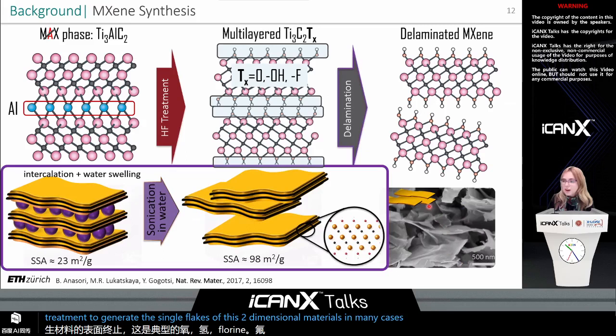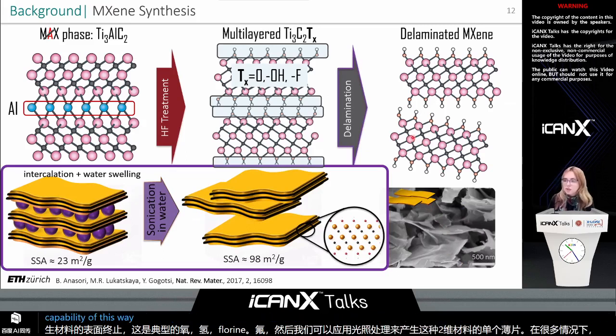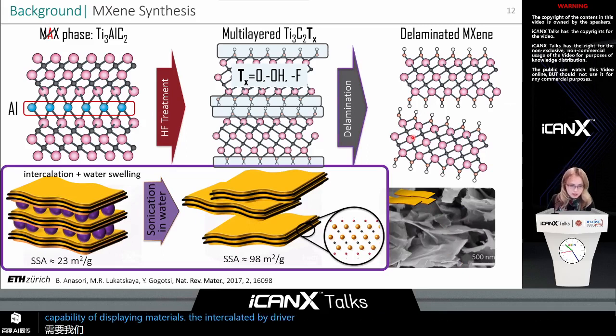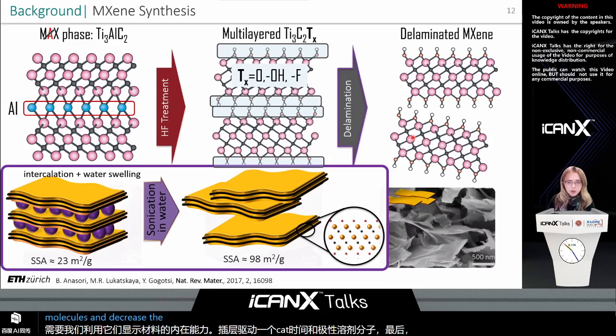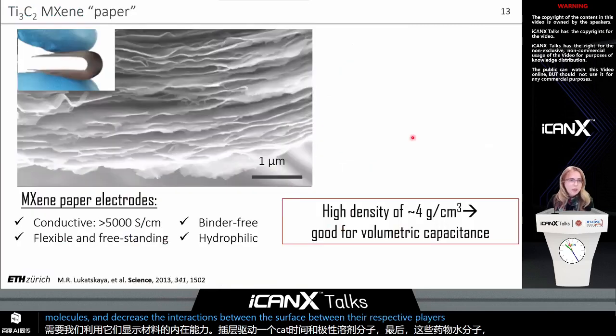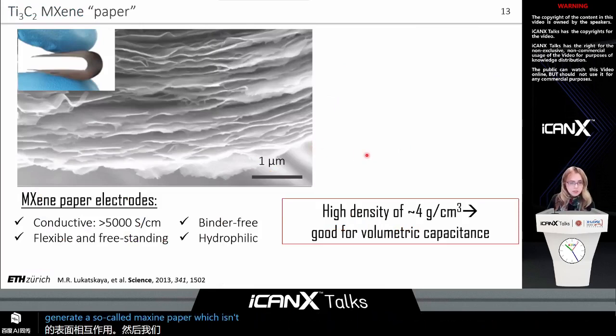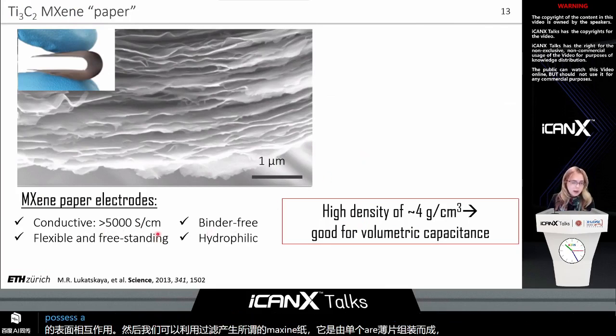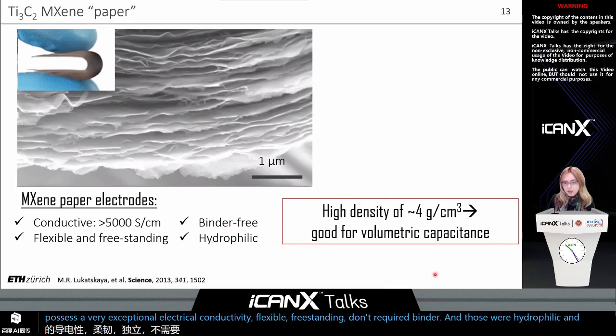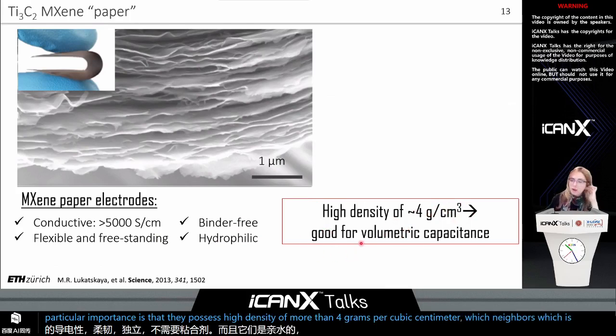In many cases, it requires us to utilize the intrinsic capability of this layered material to be intercalated by various cations and polar solvent molecules, which in the end also drag water molecules and decrease the interactions between the respective layers. Then we can use filtration and generate so-called MXene paper, which is an assembly of the single flakes and can right away be used as electrodes. They possess very exceptional electrical conductivity, are flexible, freestanding, don't require binder, and are also hydrophilic. Of particular importance is that they possess a high density of more than 4 grams per cubic centimeter, which is very important for high volumetric capacitance.